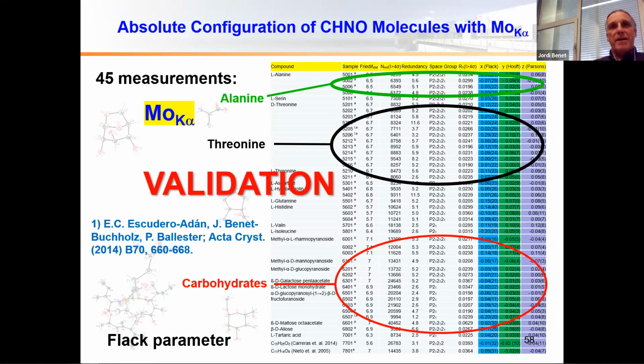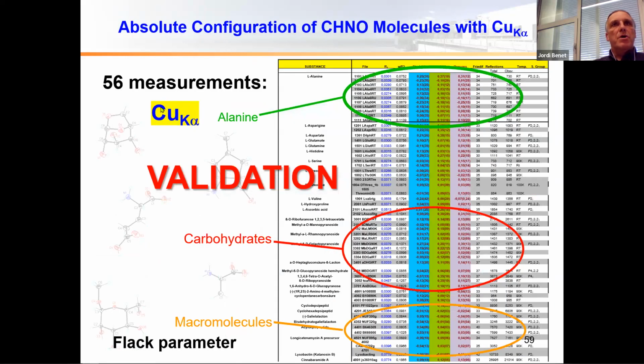So after reflecting about this, we started to make a validation. You don't need to see any number here, it's just to show you that we validated the absolute structure determination, or chirality determination, of pharmaceutical compounds, making several measurements of non-chiral molecules using molybdenum and determining the Flack parameter, which is the parameter which gives you the correct information about the chirality. We did the same using copper radiation. We measured several crystals and samples until we were sure that we had a validated method using our devices, so that we could, without any bad thinking, give a result to our customers.